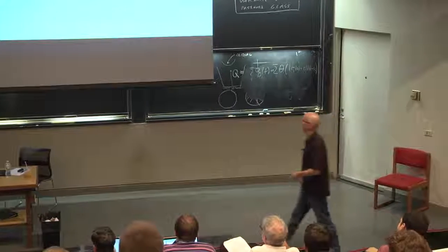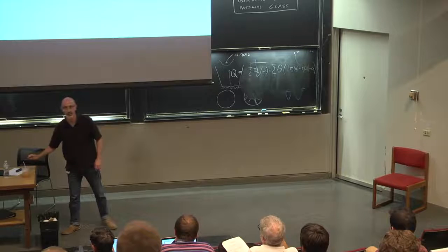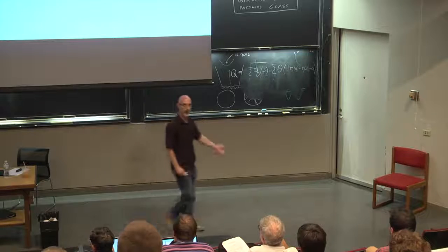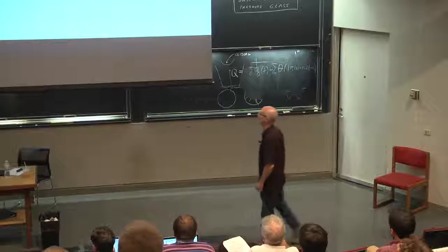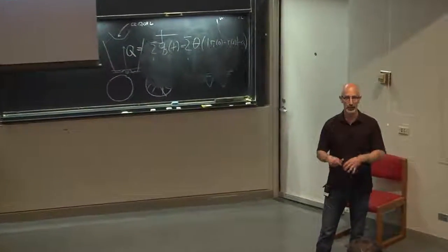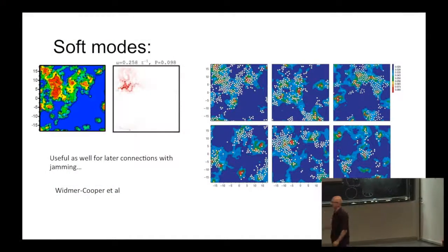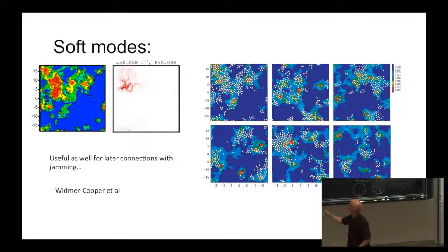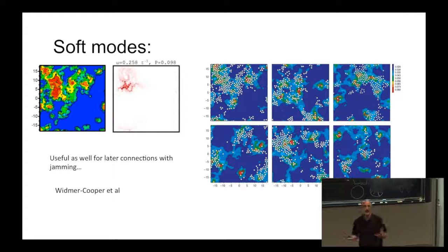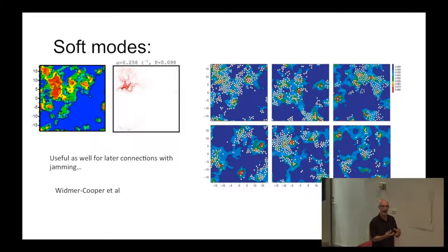So you can look at the polarization of modes. You'll find lots of different interesting features, and it would take 2 hours to just have a talk about soft modes, but some of these modes will just look like plane waves, right? So you'll see some intermixing between plane wave-like behavior. Some of these modes will be very, very localized, so the polarization would just be a few particles. And some of them are some hybridization of a plane wave and some very localized feature.